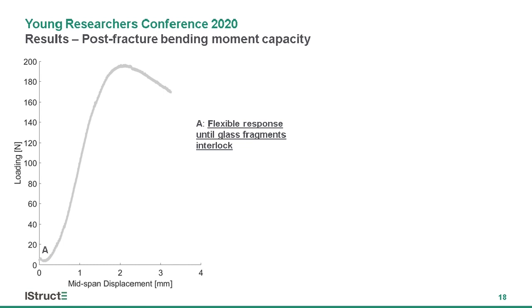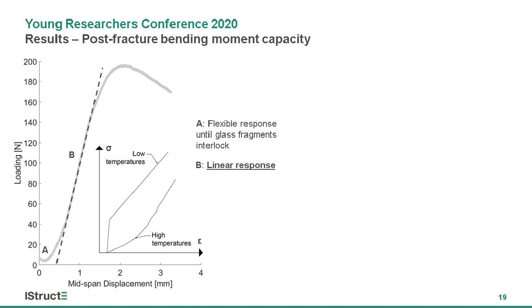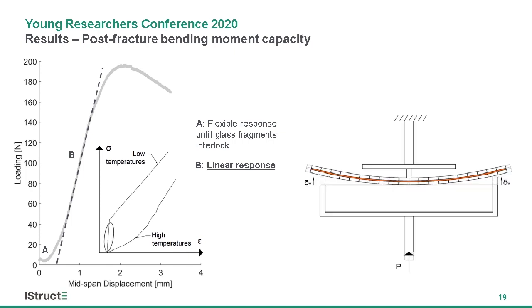Following the initial flexible response until the glass fragments lock in, a linear response is observed and the fractured panel bends elastically in a composite manner. At this stage, the PVB is in the initial slope of the stress strain diagram, and although it resembles an elastic material, it remains viscoelastic.